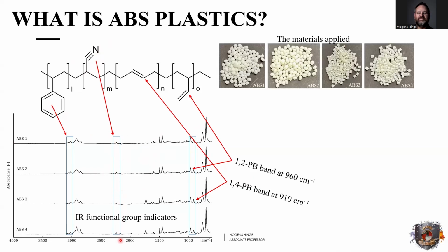It's always there. And then we have the butadiene, and depending on how they're incorporated into the material, they will both be present, but depending on how they're incorporated, they will have peaks in different places. So if we take the 1,2 butadiene, it normally has a peak here around 960 reciprocal centimeters. But if we then take the 1,4, then the double bond will have a higher energy level and therefore have a band around the 910.